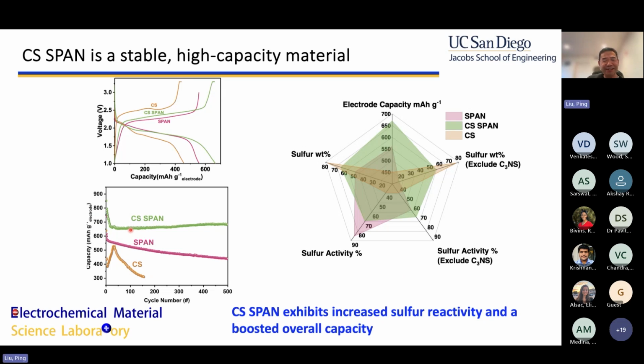It doesn't sound like a lot. It's actually a lot. If we could increase the cathode material by about 20%, we are safely in a region to produce a lithium-sulfur cell with the energy density somewhere between 350 to 400 watt-hour per kilogram, which will be wonderful. However, there's a limit to how much extra sulfur we can shuffle into the material.